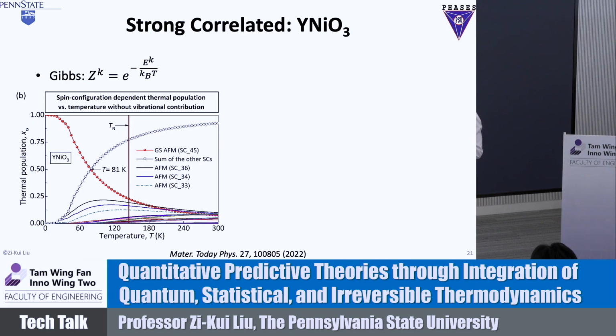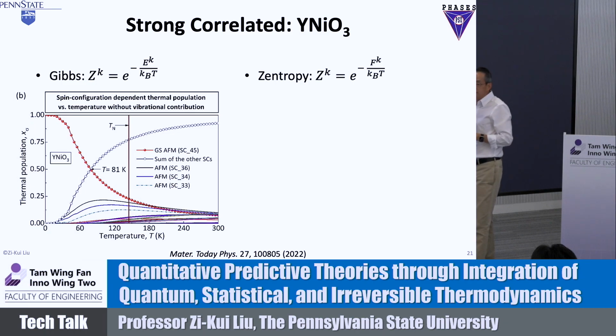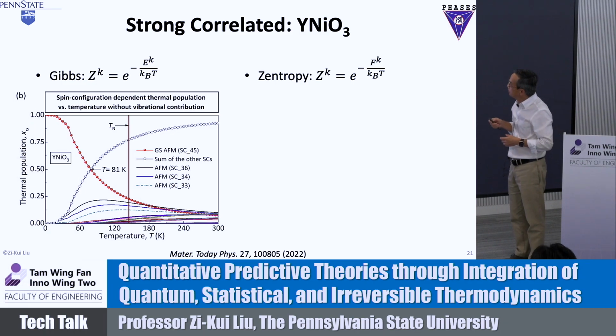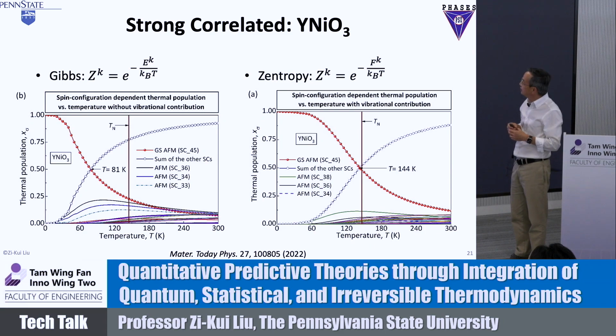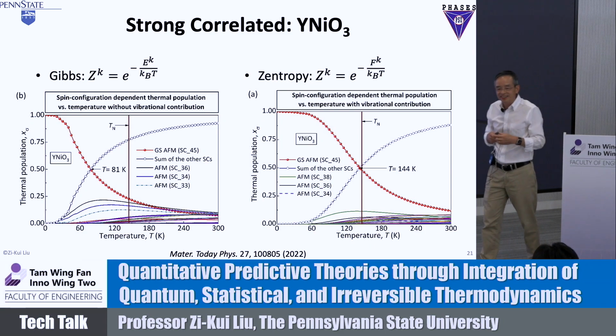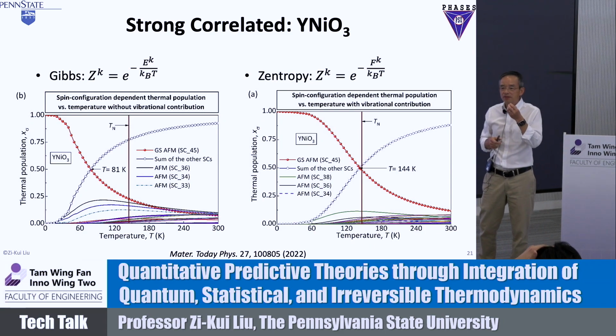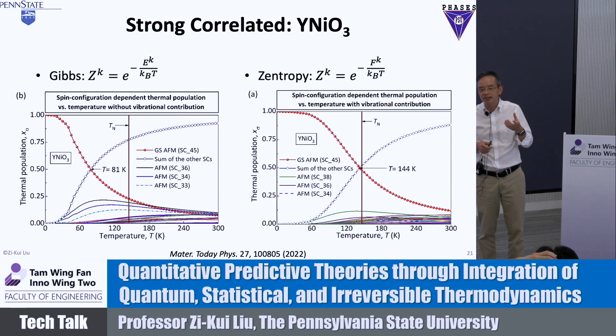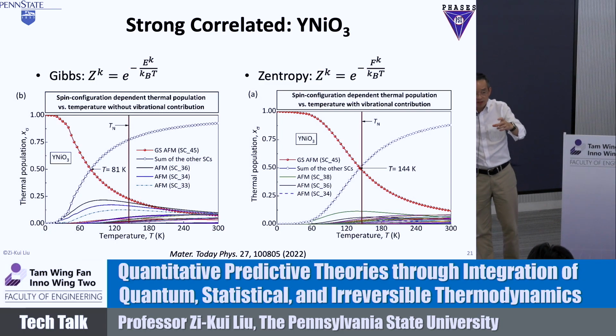And then we say, if we take the free energy one, the new statistical mechanics, the crossover is 144 degrees, and the experiment is 145 degrees. So the question is how you define that 50% as a transition, right? If you sample the system in the experiment, and the majority of your sampling is ground state, you will find it's ground state. But as soon as the ground state becomes less than 50%, when you sample it, you don't see the ground state anymore. Okay? Your sample is not a ground state anymore. That's why you get this transition.